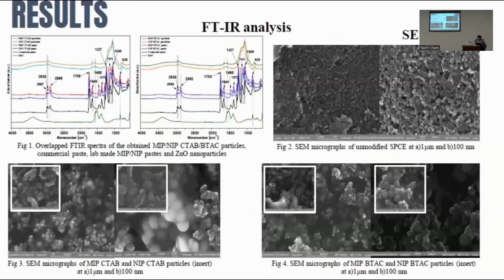Modern techniques, including structural and morphological analysis, were employed to characterize the obtained MIP and NIP particles and the final MIP-modified carbon-based formulation. The FTIR analysis demonstrates the successful incorporation of MIP particles into the carbon paste, comparing all infrared spectra. The polymers reveal the basic structure and the same characteristic bands of the organic and inorganic matrix formed during polycondensation.